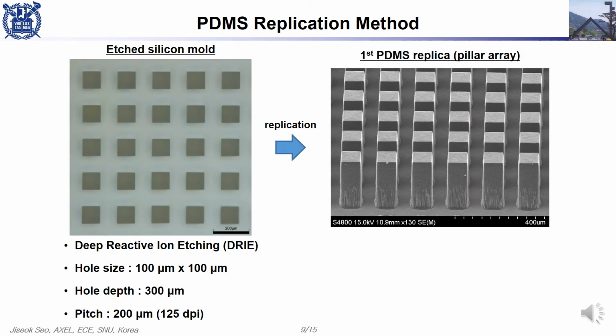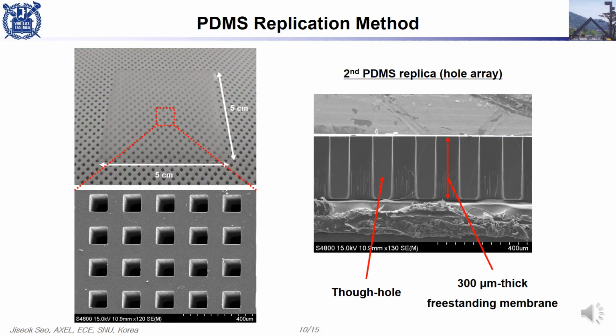This image shows the DRIE etched silicon mold that shows hole size of 100 by 100 micrometer and hole depth of 300 micrometer. The pitch between each pixel is 200 micrometer and the resolution is about 125 dpi. After first replication process, as you can see at this SEM image, the pillar arrays of same scale with silicon mold were successfully obtained. After the second replication process, freestanding through-hole PDMS membrane was fabricated.